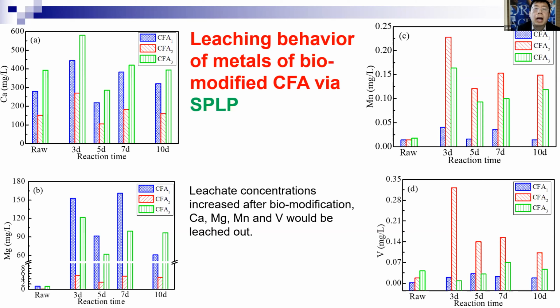which is also leaching out. So this is a kind of upside down compared with the aluminum, barium, and chromium. For those three, the metal leaching is less, but for these four, it is leaching out. So you can see this is the behavior change after you bio-modify this fly ash.